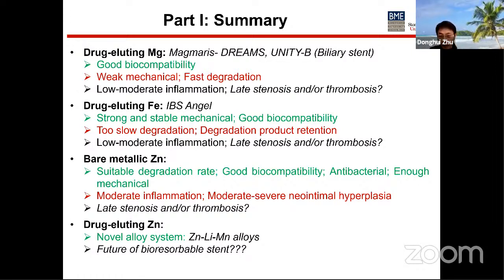For the bare metallic zinc, so far in the animal model, it showed a very good degradation rate, quite suitable, not too slow or too fast, good biocompatibility, some add-on beneficial features like antibacterial property, and mechanical property after alloying with lithium and manganese was excellent. The inflammation was moderate. Some moderate to severe neointimal hyperplasia were observed in the pig model. Of course, the late stenosis, very late stenosis, and thrombosis need further evaluation.